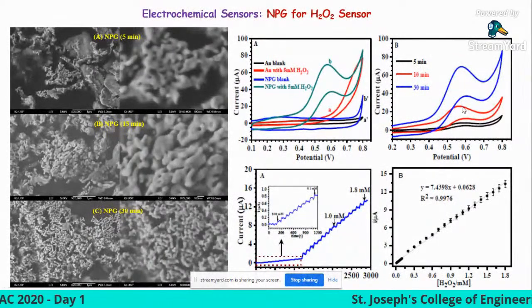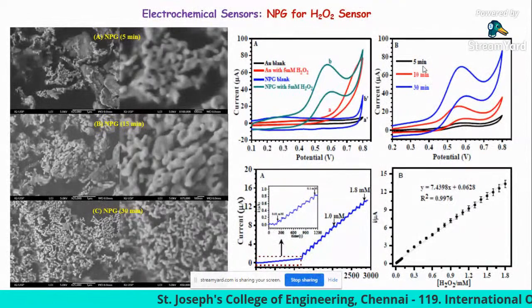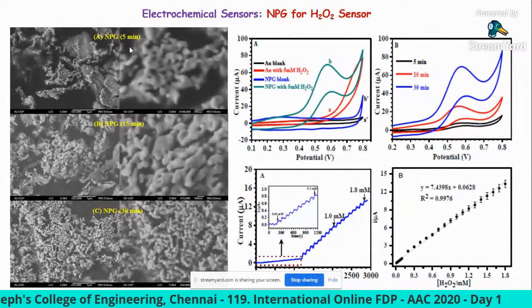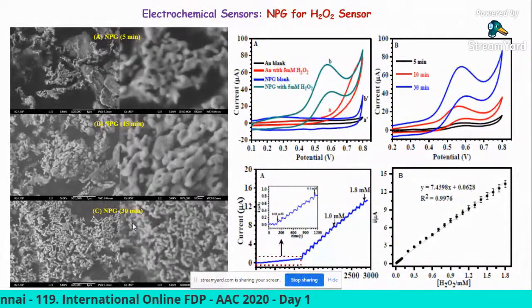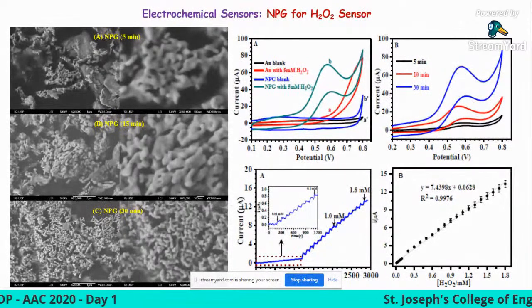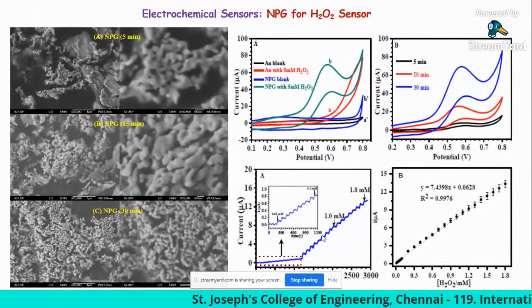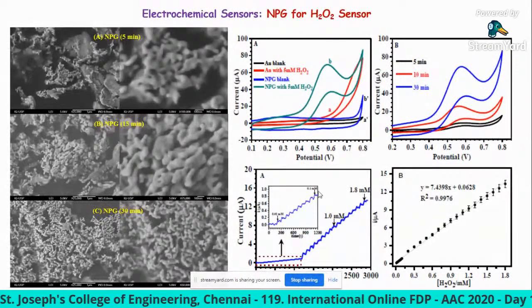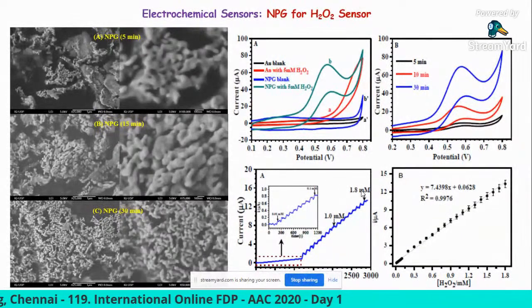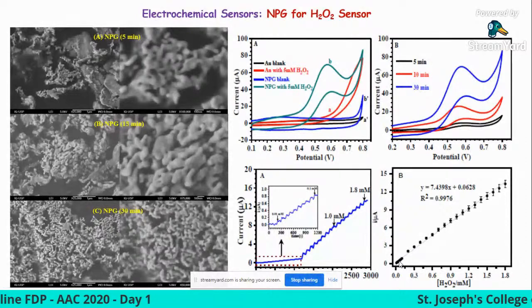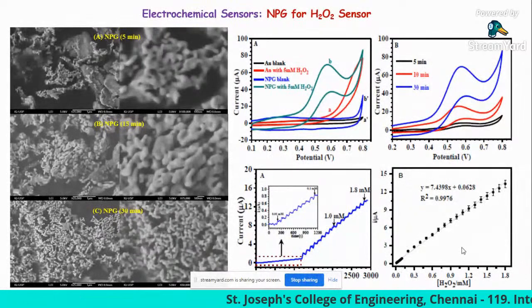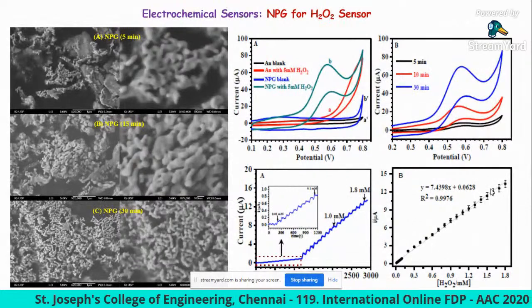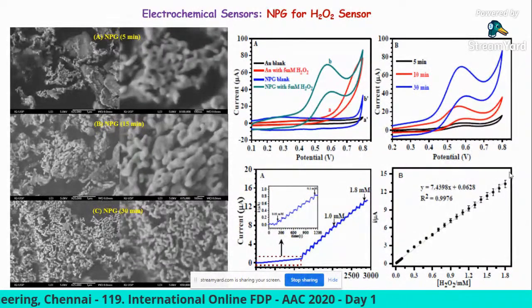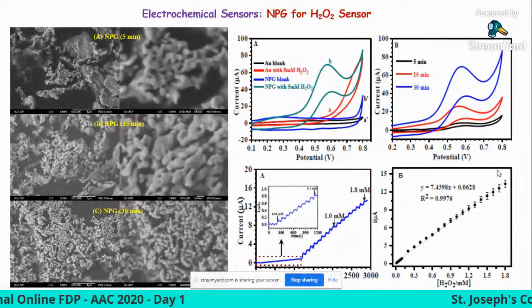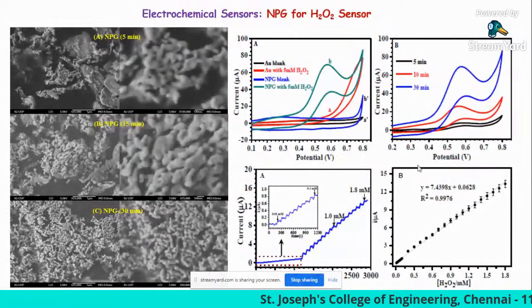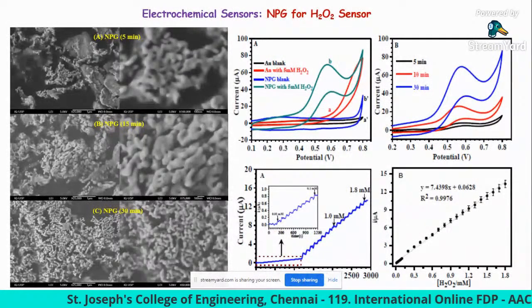These are the cyclic voltammetric responses for hydrogen peroxide oxidation at different anodization times. When you increase the anodization time, the electrochemical surface area also increases, and that's why the current signal also increases. This is the corresponding amperometric response. We performed the experiment from 10 micromolar to 1.8 millimolar, where the hydrogen peroxide oxidation current signal increases linearly with the addition of hydrogen peroxide concentration. Using the slope of this value, we can calculate the minimum detection limit of the hydrogen peroxide sensor. This work we recently published in the Journal of the Electrochemical Society, I think 2 weeks ago.